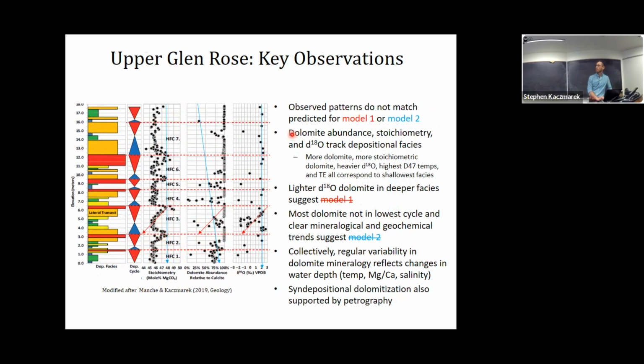What we see is dolomite abundance, stoichiometry, and delta O18 all track with depositional facies. As the facies become deeper and then shallower, dolomite abundance decreases and then increases, stoichiometry decreases and then increases, and delta O18 values decrease and increase. The more dolomite we have, the more stoichiometric it is, and the heavier the oxygen isotopes. Those same samples also show our highest delta 47 crystallization temperatures and the highest concentrations of trace elements.